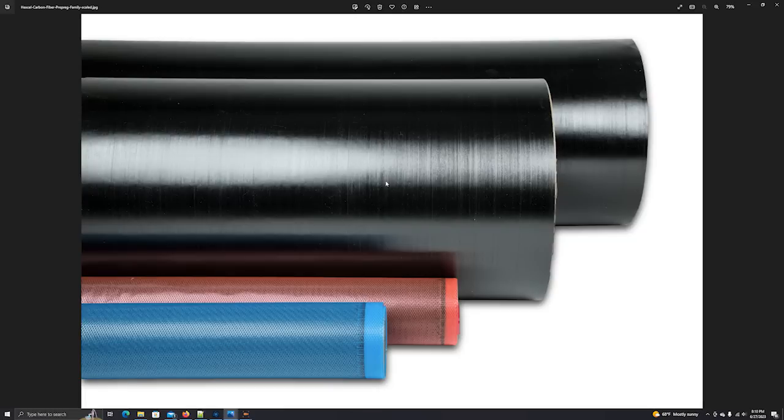Again, the benefit of using the prepreg material is the epoxy to fabric ratio is metered very carefully, so you get the same amount of resin per fiber ratio exactly across all the plies when you're laying this up. Now again, the Titan had 5 inches of carbon fiber thickness, so that is a lot of plies. And if you watch the video, you notice that the carbon fiber tow is very, very thin. So that means they used a tremendous amount of carbon to wrap around that cylinder. And again, it was done with a wet process. So you have to question how accurate is the epoxy to fiber ratio in a filament winding process where they actually wetted out the carbon fiber by hand.